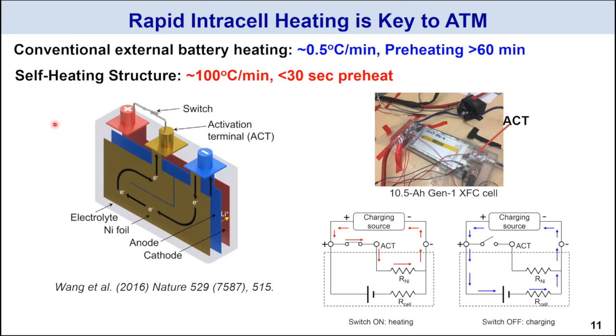Now, in our research, we use a self-heating structure, which we first published in 2016. So it's actually a very simple construction. You take a pouch cell, which is typically 10 millimeter thick, and then you insert a nickel foil, which is only 10 micron thickness, shown here as a yellow sheet. There are two ends of the nickel foil. One is welded to the negative terminal, and the other is sticking out to form a third terminal. We call it the activation terminal. And then you place a switch between the positive and activation terminal.